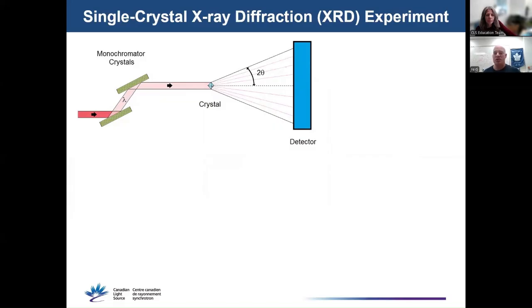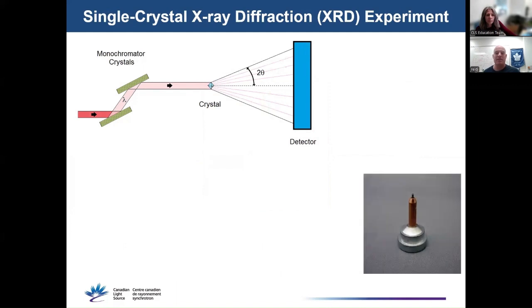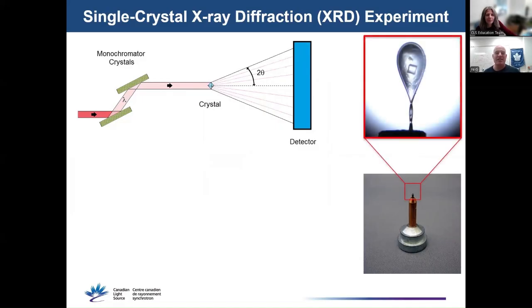Here's what a single crystal diffraction experiment looks like. So the crystal is mounted on a metal base like this, that's roughly an inch in height. To actually see the crystal, we need to zoom in on the top of the base. And the crystal is this small cube in the center of this loop. This crystal is on the order of 0.1 millimeters or 100 micrometers in size. So it's not very big.